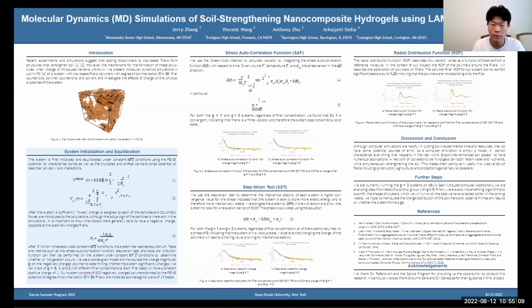Next, we equilibrate our systems under constant NPT conditions with the finitely extensible nonlinear elastic potential to describe the polymer bonds, the soft potential, the Lennard-Jones potential to characterize dispersion forces, and the electrostatic potential to describe pairwise interactions between charged particles. After equilibrium, we'll perform 3 tests under constant NVT conditions: the stress autocorrelation function, the step strain test, and the radial distribution function. Using the Green-Kubo relations, the stress autocorrelation function allows us to determine the system's viscosity by integrating from 0 to infinity with respect to time.